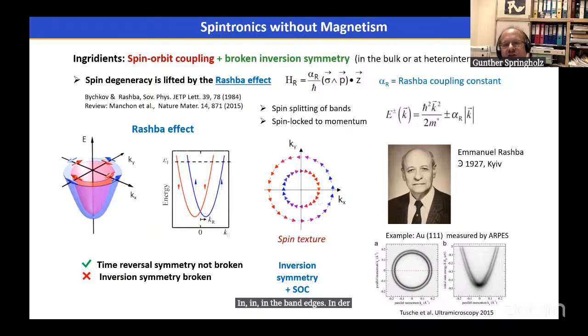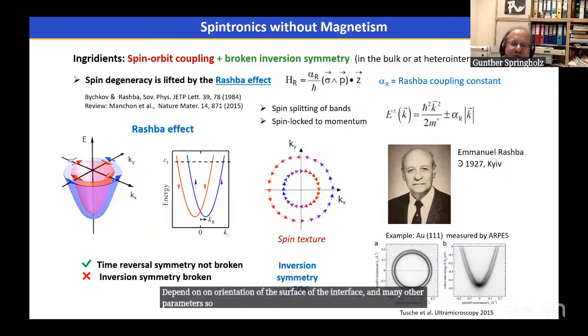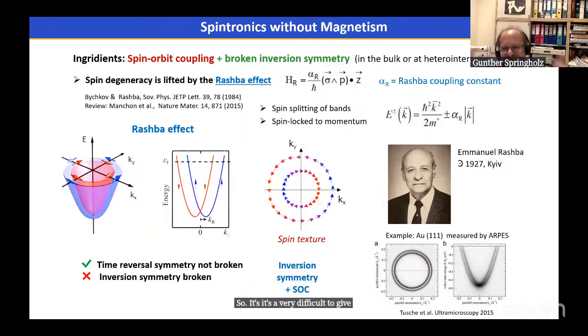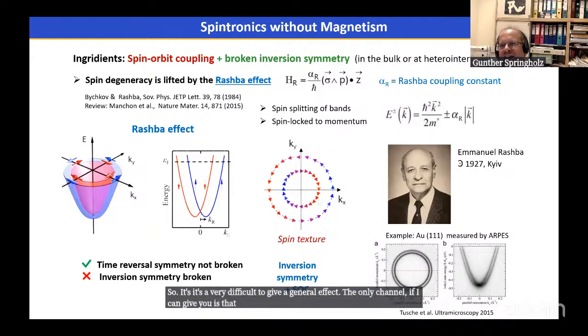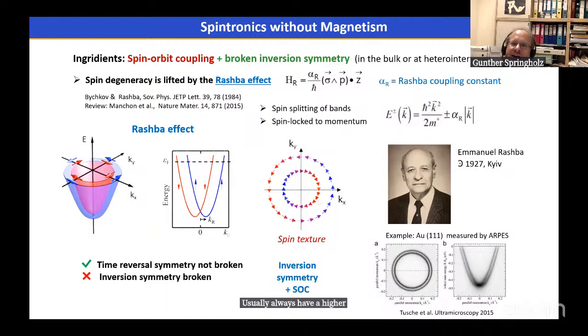and these gradients in the band edges are similar to the action of an electric field and depend on growth parameters, orientation of the surface or of the interface, and many other parameters. So it's very difficult to give a general answer. The only general answer I can give you is that materials with heavy elements usually always have a higher spin-orbit coupling compared to compounds with light elements. Yeah, thank you.